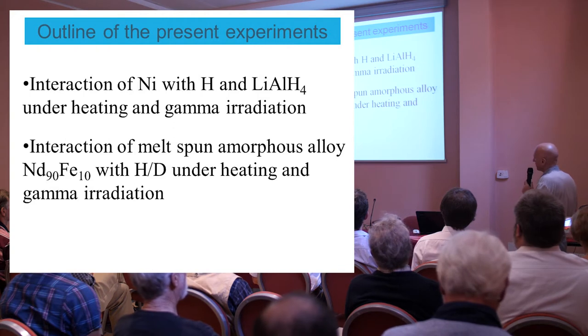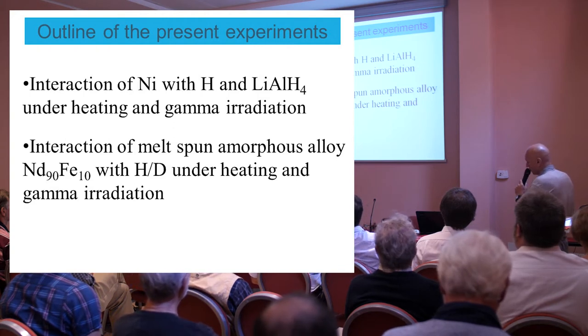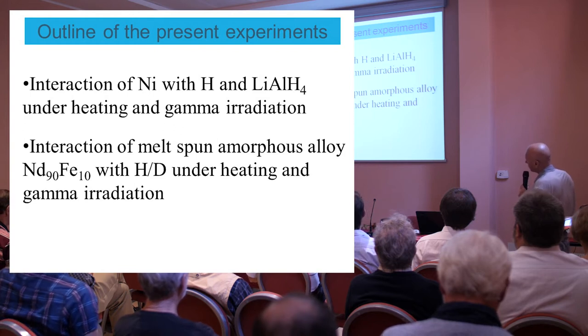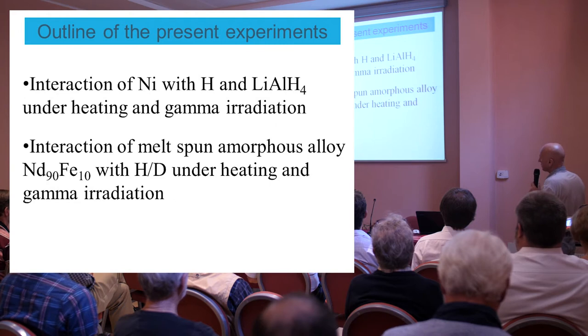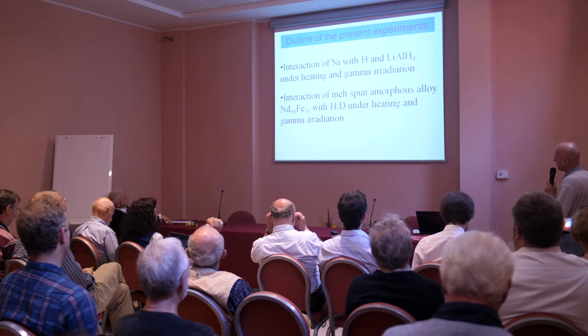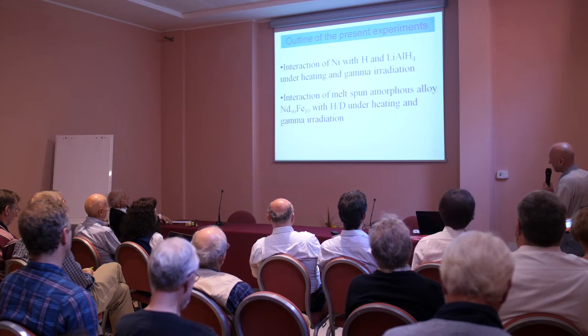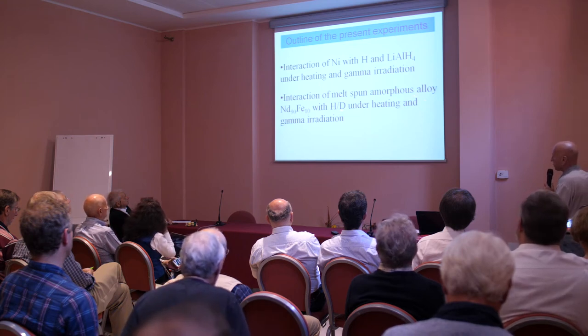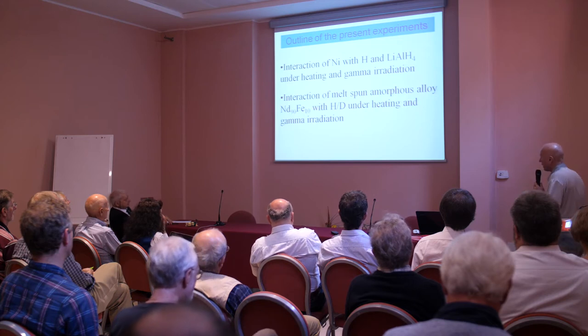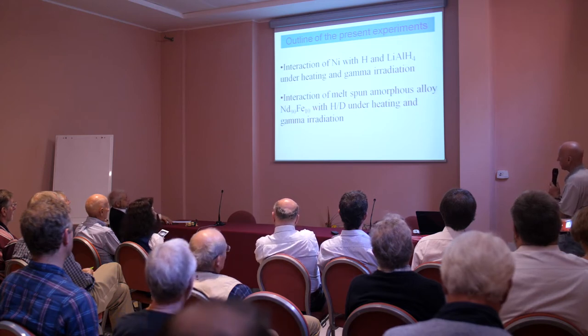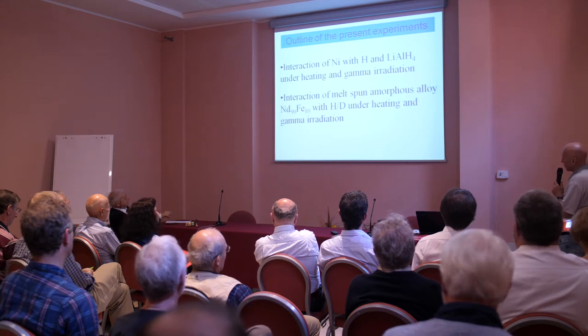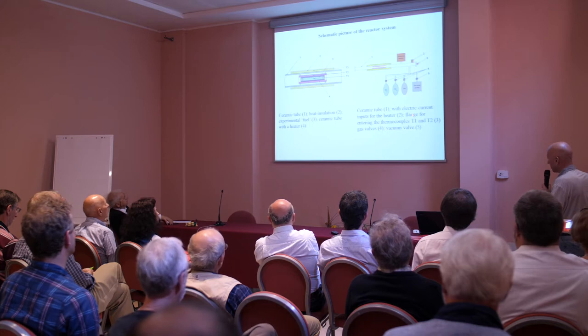And now we have this opportunity, and I would like to present you two such experiments. One is the interaction of nickel powder with hydrogen and lithium aluminum hydride under heating and also under gamma irradiation, a combined action. And another one is a new material that we try to test, which is a melt spun amorphous alloy neodymium ferrum. Also, we tried it with a hydrogen, deuterium atmosphere, also under heating and under irradiation.